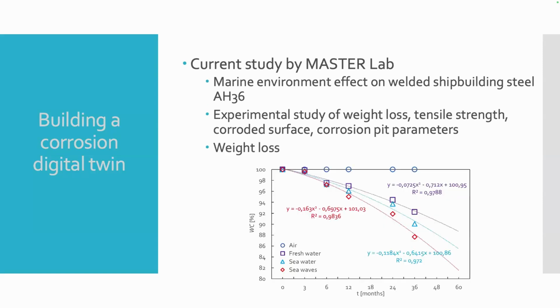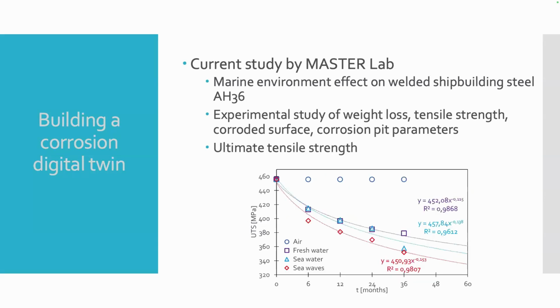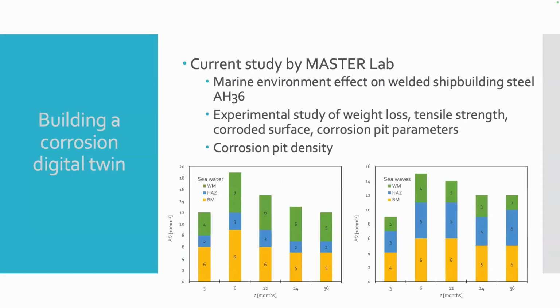Here are some of the diagrams that are also published, and you can check them in the journal papers. We have accounted for the weight loss, tried to do some kind of regression analysis, to see how well the steel will behave in the future time of exposure, future periods. We have done testing of the ultimate tensile strength and seen the drop of the apparent tensile strength of this type of steel, also fitting some curves through the experimentally obtained data to see how well they will behave in the time ahead of us.